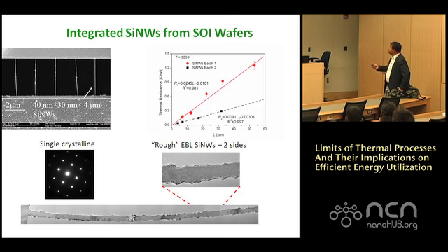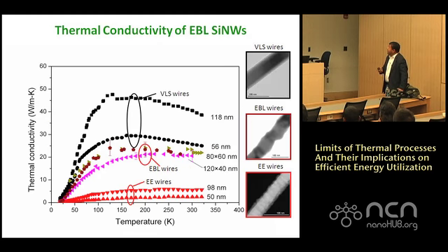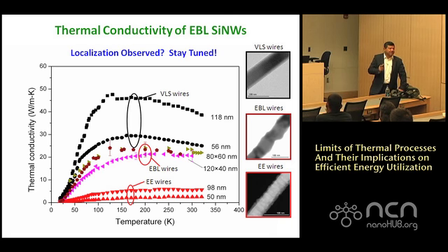We have measured the thermal resistance as a function of length. The good news is that as you reduce the length, the resistance goes to zero, which means there is no contact resistance, which is a good thing, because people have been asking us questions about our previous data. This is data showing that. We have now also made the first few measurements of thermal conductivity as a function of temperature of these VLS wires that I showed you. This is the electron beam lithography, slightly roughened. These are the really roughened wires of EE. And we're seeing at least the right order of magnitude. Have we seen localization yet? Not yet, but stay tuned. This is the experiment that we're trying, and only the data will show us how it goes.